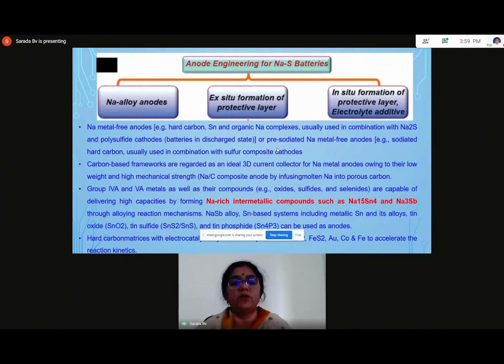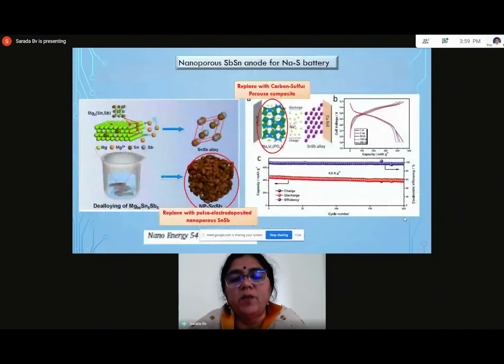So in case of sodium sulfur batteries, mainly your sodium ingots are used as anodes. But as I said, with cycle life, with very few number of cycles, the dissolution of these polysulfides, forming polysulfides along with sodium, and also forming dendrites of sodium at the interface decreases the performance of the battery. And in order to decrease that, you can use the alloys of sodium antimony, sodium tin antimony alloys, so that this problem will be solved.